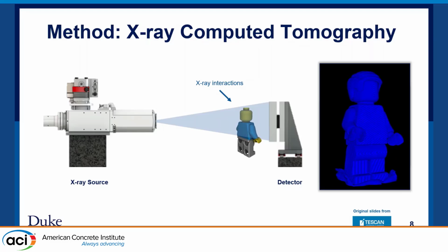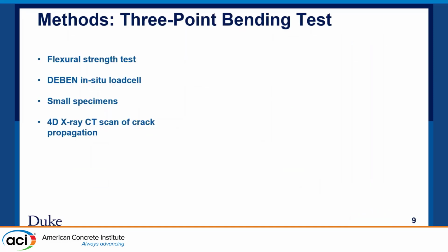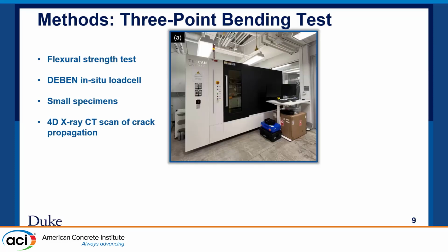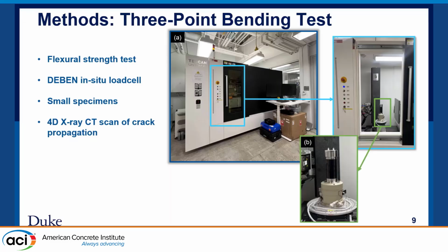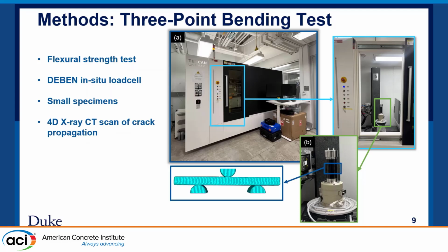So this method can be used for non-destructive as well as destructive tests we want to do for the samples. For the 3-point bending test, we use this machine by TESCAN that is named Unitom XL. This is an X-ray CT machine that we use for the 3-point bending test. It has a Deben stage in situ load cell that mounts the sample to be tested and scanned throughout the time and throughout the loading, and gives the 4D X-ray CT scan of crack propagation.